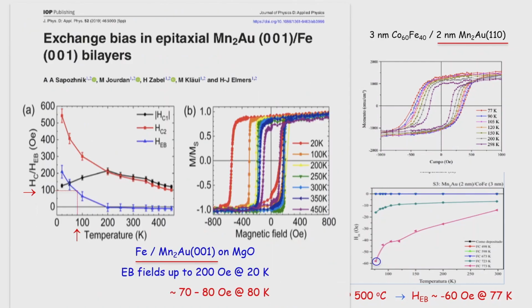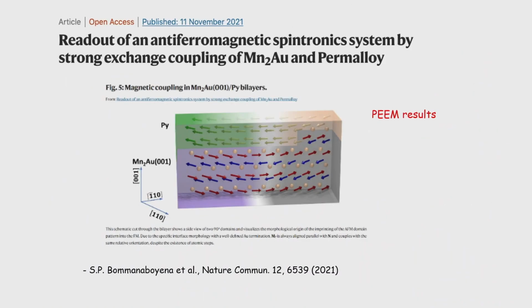we see that what we get is very much the same as what the German group got recently with the same material, but in another orientation, the 001. Here we have a 110, but the exchange bias at 80 K is very much the same. That means you are not far away from what the groups are getting today with this material. But that's to show that it's really interesting. This is a Nature paper,